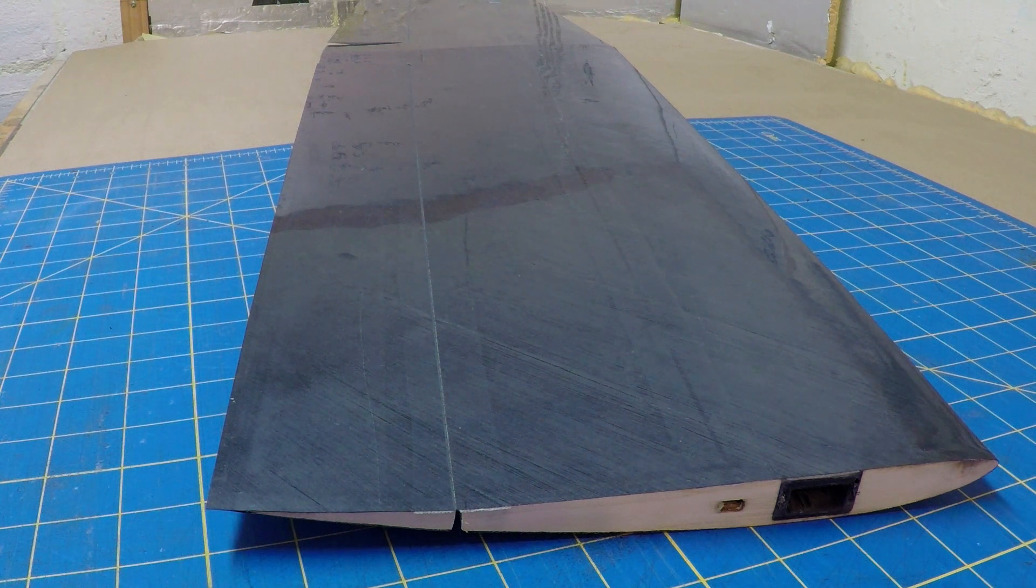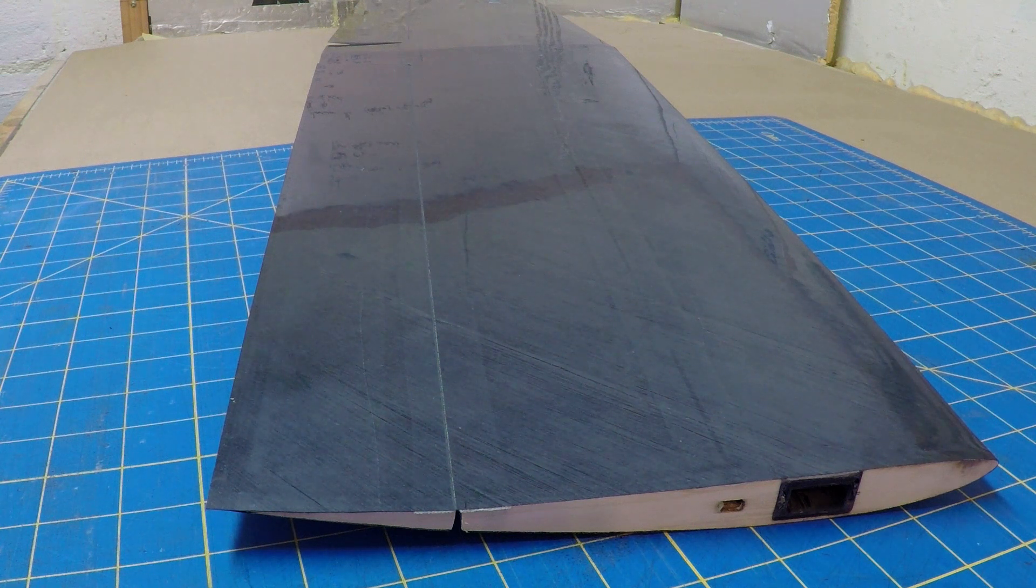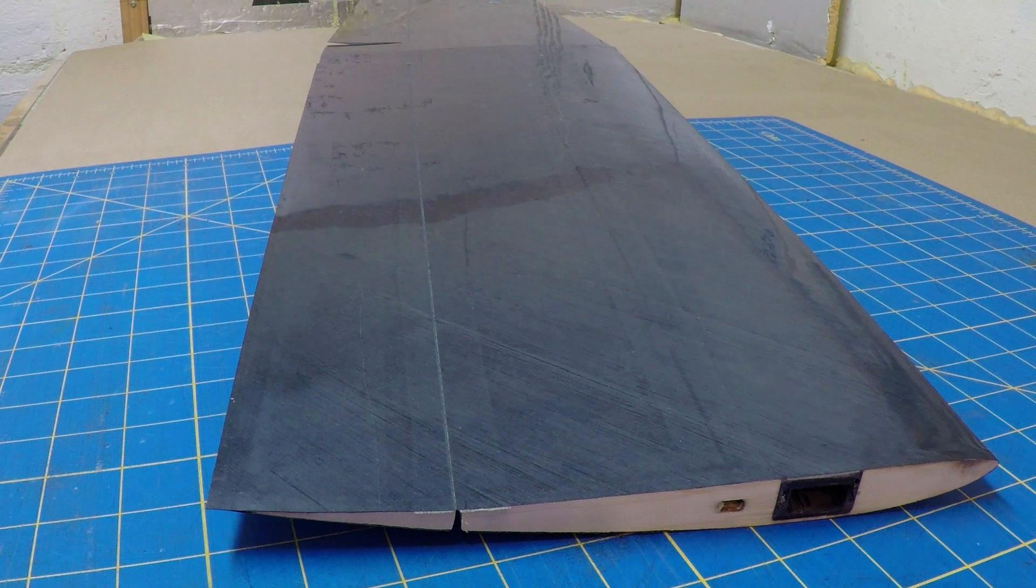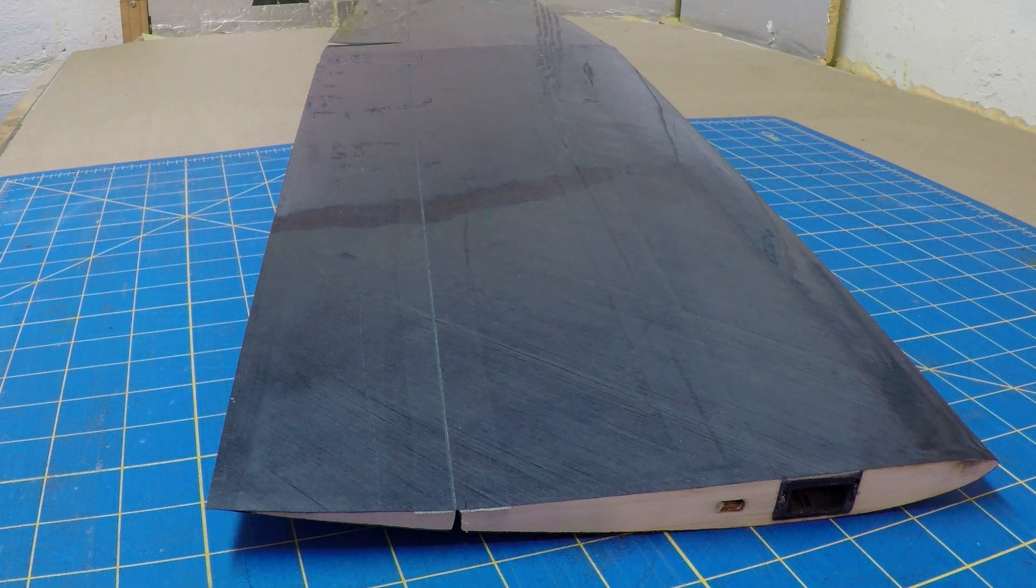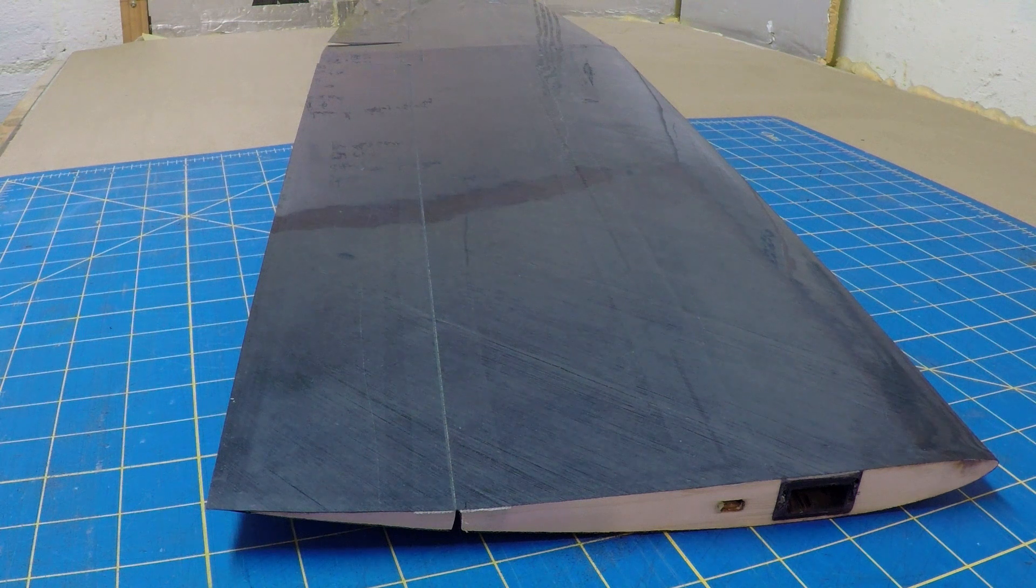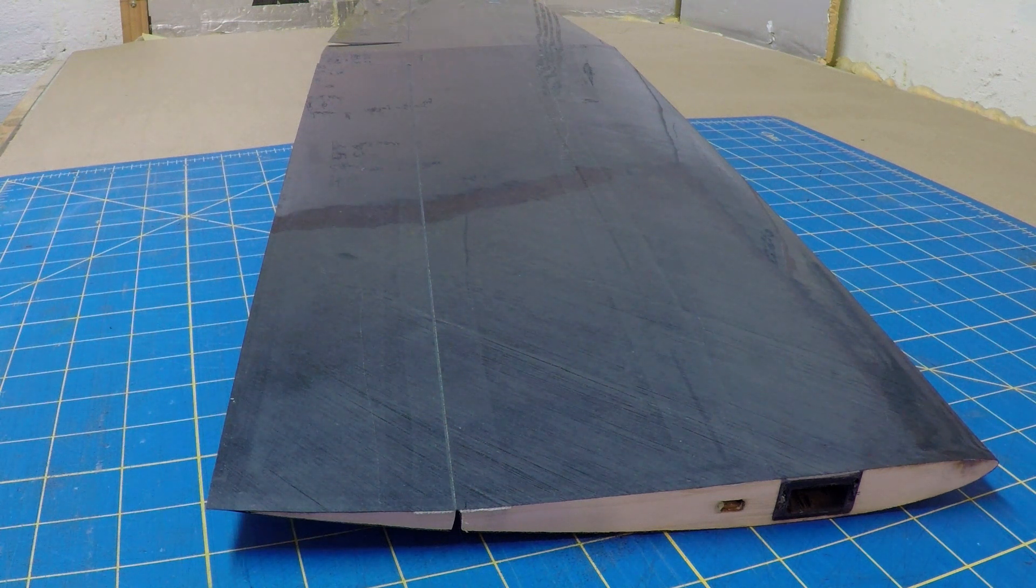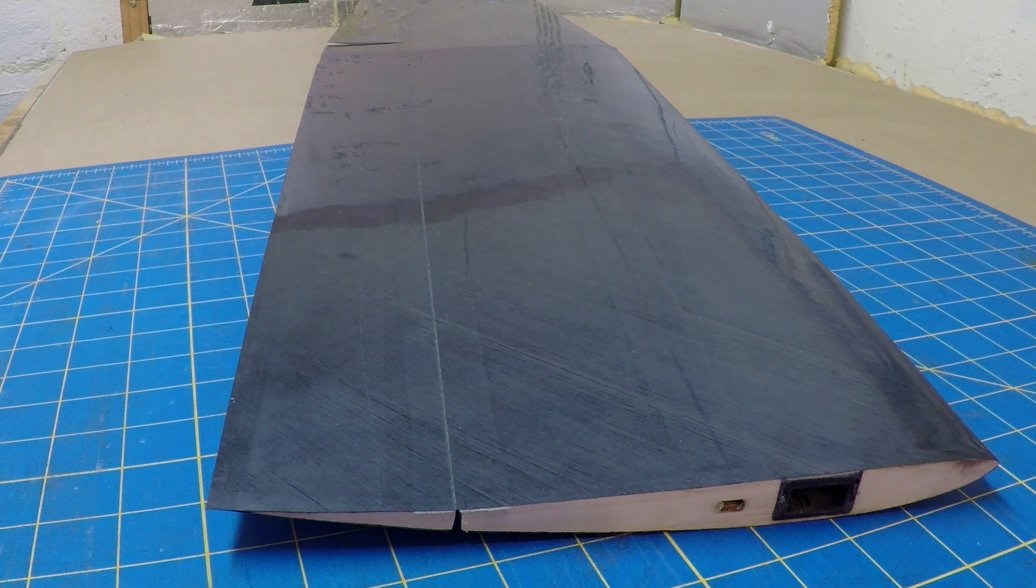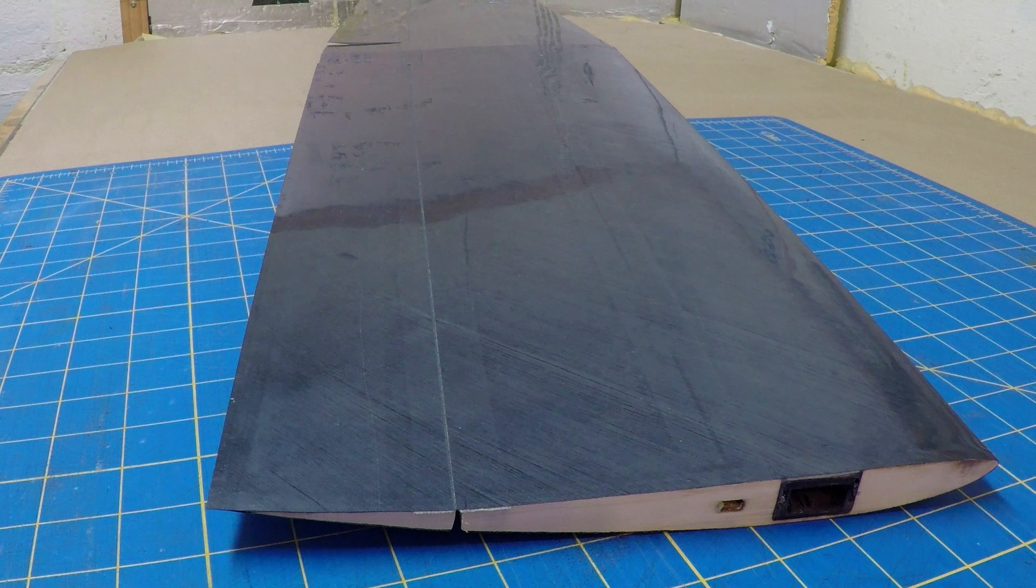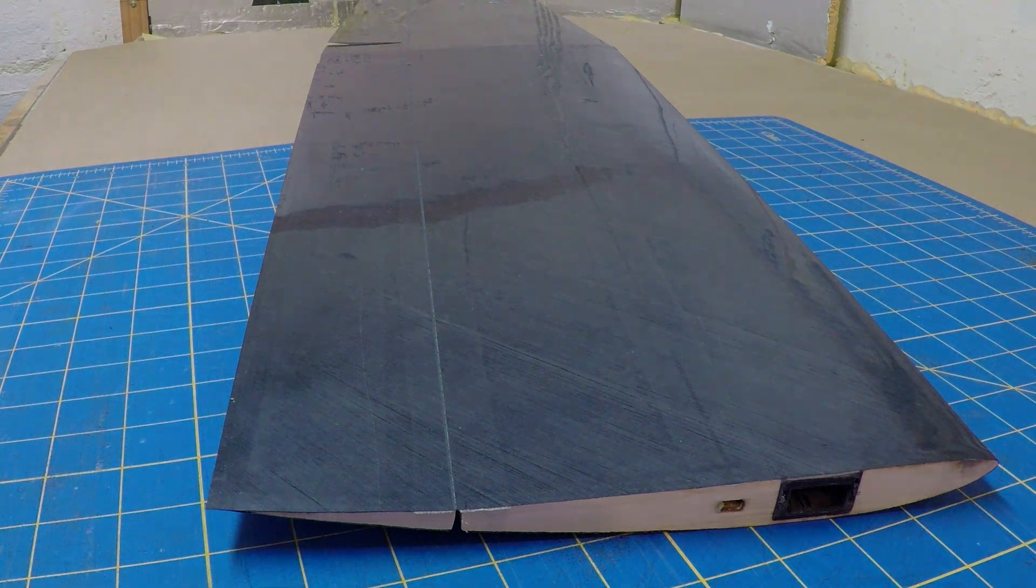I used to face control surfaces, but I've found that most of my delamination issues were from the center panel separating on hard landings. So the drag spar has seemed to cure my delam issues of the hinges, and I found that it just wasn't worth the time and effort and extra weight to continue to face my control surfaces. I know structurally it's the right thing to do, but I've gotten away from it.